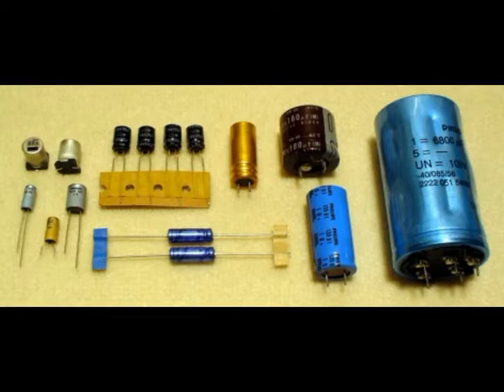One of the aluminum foils, the anode, is etched roughened to increase the surface and oxidized formed. The second aluminum foil, called the cathode foil, serves to make electrical contact with the electrolyte. A paper spacer mechanically separates the foils to avoid direct metallic contact. Both foils and the spacer are wound and the winding is impregnated with liquid electrolyte. The electrolyte, which serves as cathode of the capacitor, covers the etched rough structure of the oxide layer on the anode perfectly and makes the increased anode surface effectual.